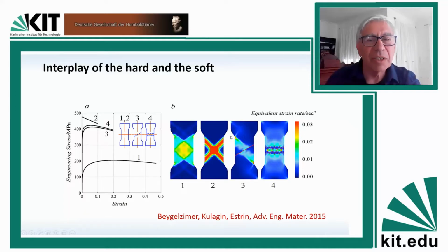by strain localization in this way, the hot red areas here. But if you introduce just one layer of soft material here, you kind of diffuse the propagation of damage, and you get a behavior shown by curve 3. So it is not as ductile as 1, it is not as strong as 2, but the combination of properties is much more favorable. So it's tolerant to plastic deformation to some extent, and it has not lost a lot of the load-bearing capability of the strong initial material.